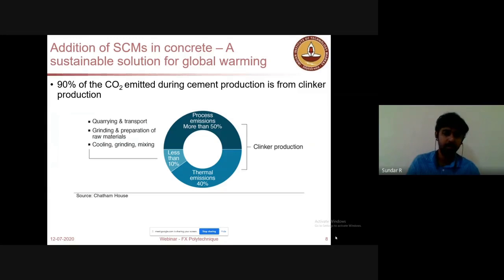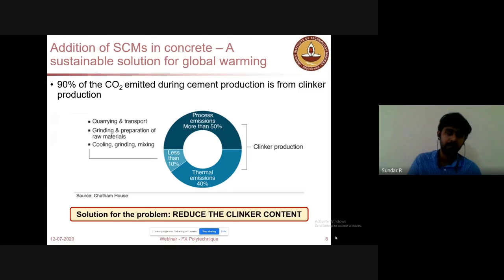So those are very minimal. So when you look at this, you could see almost this process itself is contributing to the 50% of the emissions. And you can see thermal emission also contributing a lot, but that will be dealt by using some alternative fuels. However, as material scientists and civil engineers, we can have an idea about reducing CO2 by reducing the clinker content by the addition of SCM.